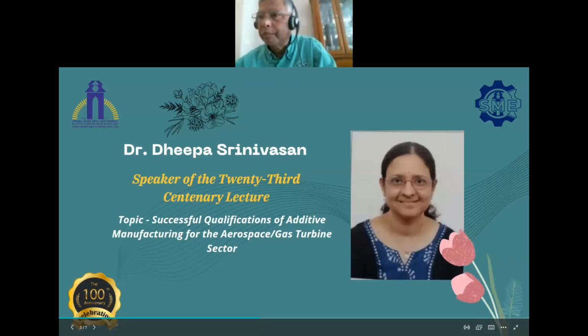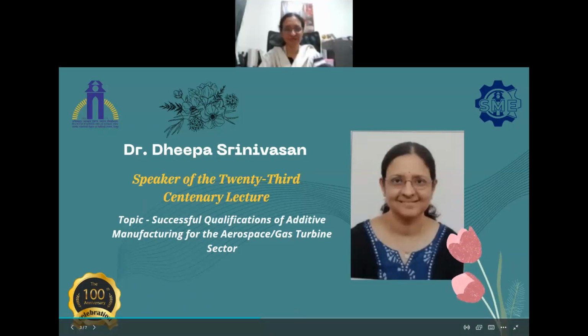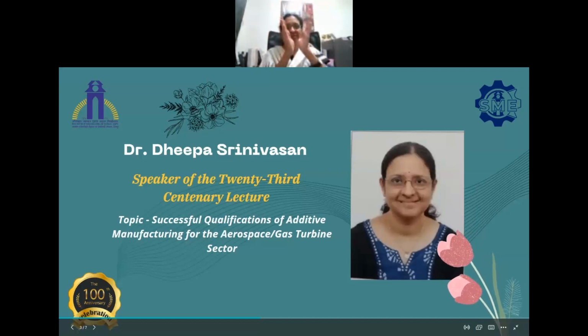It's a constant endeavor to continue to change particle size distribution. So it's a very good question. Thanks for that. In the direct energy deposition process, we actually use upwards of 50 to about 150 microns, because there you have a coaxial nozzle. It is a cousin of cladding, except that the nozzles use either wires or powders.